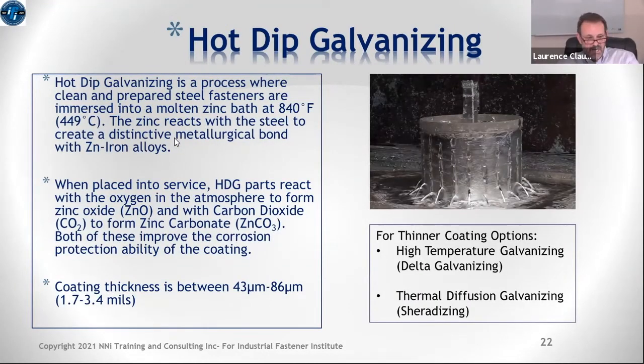Okay, hot dip galvanizing then is the process where you are immersing steel parts into a molten zinc bath. The temperature of the zinc pretty much reacts with the steel to create a distinctive zinc iron alloy at that interface, and then subsequent zinc that builds up on top of that has some different types of structures and so forth. But you end up with generally very thick coatings. You can see down there 43 to 86 microns. So generally thick and a lot of variation in them. That creates problems for users some of the time because of fitment issues. They can't get a nut and the bolt to fit together easily.